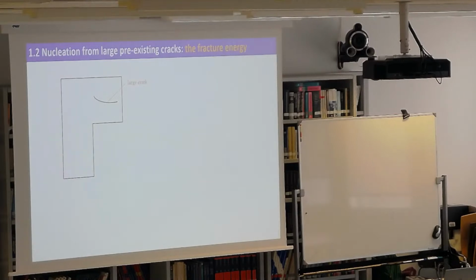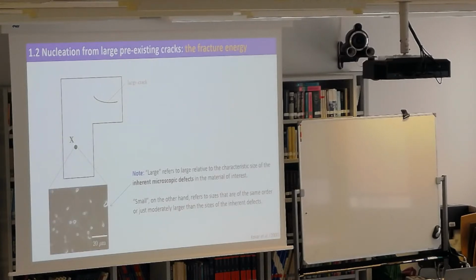Fracture energy, large crack. You go and do experiments, and now I'm going to define what large means. This is a bit tricky because we don't really know yet how to quantify it, but we're simply going to say that if the crack is much larger than the inherent microscopic defects in your domain, this is alumina, you can see here the grains, and you can see pores there, right? It was made some way, so you have defects. If your crack is much larger than this length scale, and again, I don't know how to define that, but much larger, then experimentally, this is going to nucleate from this pre-existing large crack according to this formula, right? That is famous now. Okay, so symbolically, this is what we observe experimentally. This seems to be true. Okay, so there are experiments for which you can measure GC. All right. One more ingredient. This is nucleation from a pre-existing crack. I'll talk about propagation in a second.